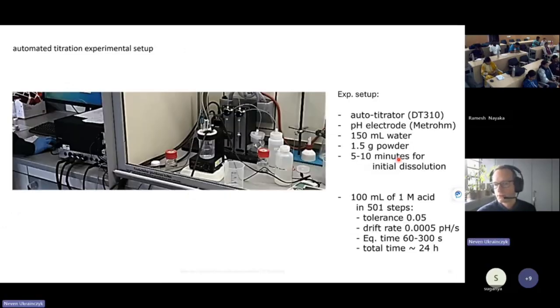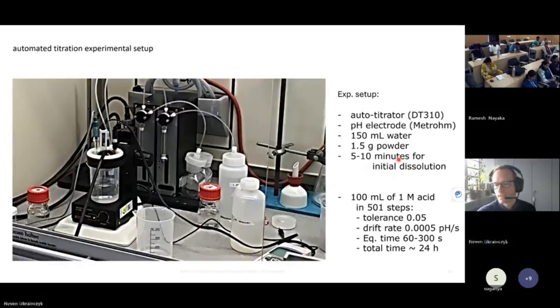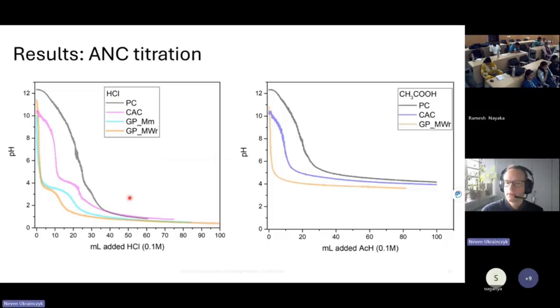Here I wanted to show you can do the pH titration experiments. Basically you are dosing acid, and then you can see the neutralization capacity of the binder. And this is very important because you can see it here. Portland cement has a very high buffering. So you are adding HCl and you are reducing the pH. It's in the powder, so this is almost equilibrium powders. You can measure the neutralization capacity of the binder.